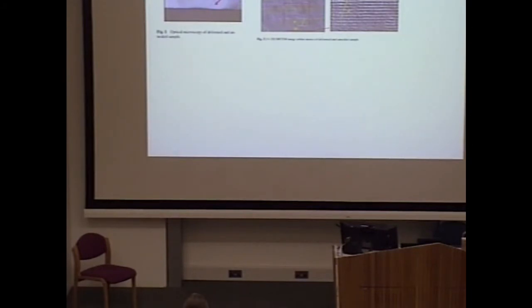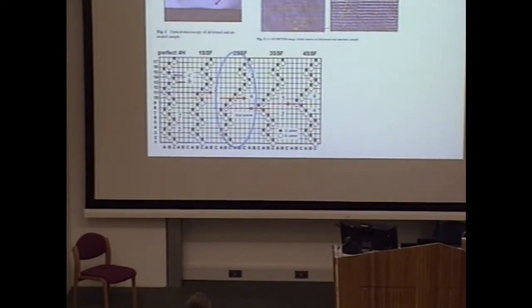First, by deformation, many partial dislocations are introduced and make stacking faults. Yeah? This is a report by Pichot in France, yeah? And this is a high-resolution image by TEM. So in this area, 4H structure and also 3C structure appear here. Just say that this is a perfect 4H structure, and one partial dislocation introduced here. Two partial dislocations also introduced here. So let's say one, two, and three stacking faults. Four stacking faults is here.